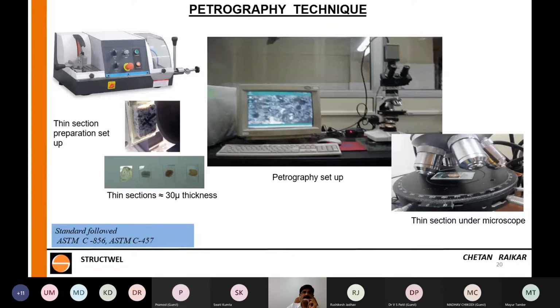This is petrography. Petrography is, as I said, see, Petra means, I think in Greek, stone. So it's a science of stone where you actually see the DNA, or a signature, of the stone. What you do is prepare a 30 micron thin stone sample by grinding. These are various types of stone samples kept on a piece of paper. These are 30 micron. 1 micron is 1,000th of a millimeter, so we are talking of 30 parts out of 1,000 parts of 1 millimeter. So it's very, very thin.